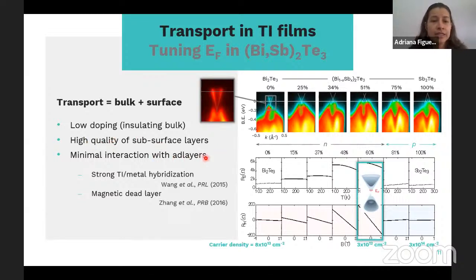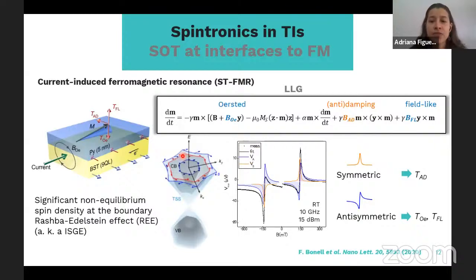And then there is another point that I like to point out here, which is that for transport, an important requirement is that you want minimal interaction with the adlayers that you have these TIs with, because it's demonstrated that there is still hybridization between the TIs and metals, and not only with metals but with ferromagnetic metals, there is usually a magnetic dead layer that happens at the interfaces with the TI. That is relevant not only for transport itself, but also for spintronics, and that's one of the first results that I wanted to show you and to talk to you about.